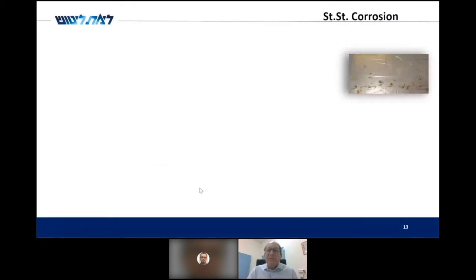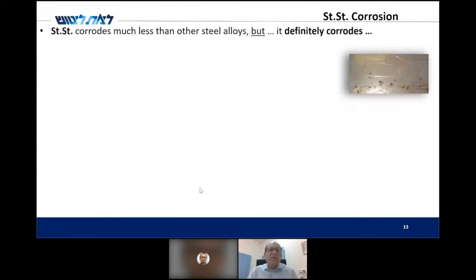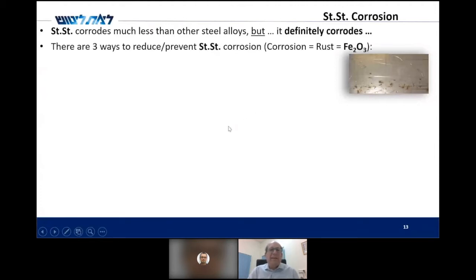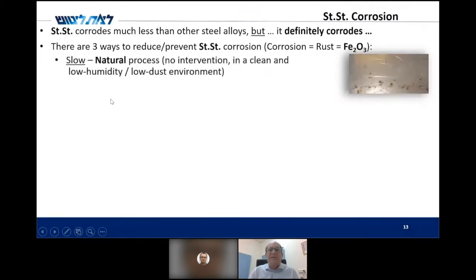So what about stainless steel corrosion? As Professor Groysman mentioned, stainless steel corrodes much less than other steels, but it definitely corrodes. And there are three ways to reduce or prevent the corrosion. If you remember, corrosion is the oxide of iron, Fe2O3. So there is a slow process, which is a natural process. If you put stainless steel in a clean, low humidity, low dust environment, it will eventually grow a buildup of protection layer, which we will discuss in a second, and will stop corroding.